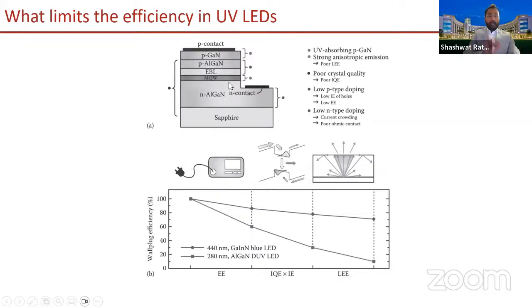There are a lot of challenges in injecting carriers into the semiconductor to start with, and there are also challenges in getting light out of the semiconductor. What happens is that these wide bandgap semiconductors have a huge difference of refractive index with air. So the light just doesn't want to come out of the semiconductor. It rather is reflected back in the semiconductor, and then you only get a low fraction of light out of the semiconductor. So these are some fundamental challenges of this technology that we are systematically working on, and eventually we aim to reach the performance of blue LEDs in the deep UV LED technology.